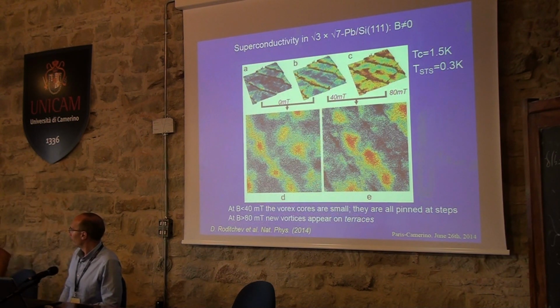These atomic steps all host these vortices, which are a specific kind of vortices predicted several years ago by Alex Gurevich. And these are neither Josephson nor Abrikosov vortices. This is a mixed kind of vortices in which you have a phase gradient which has a partial jump on the atomic step, but you still have a vortex core.